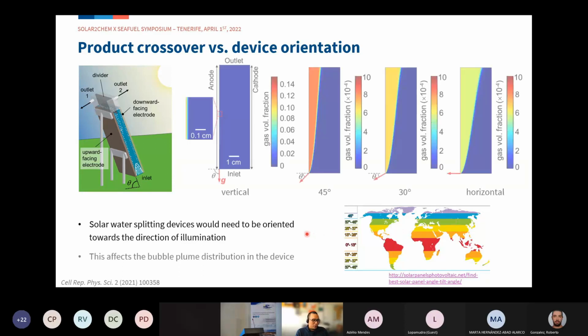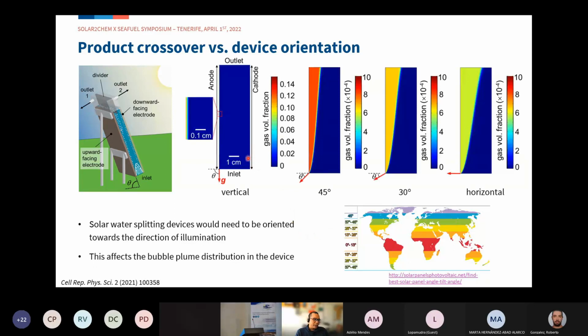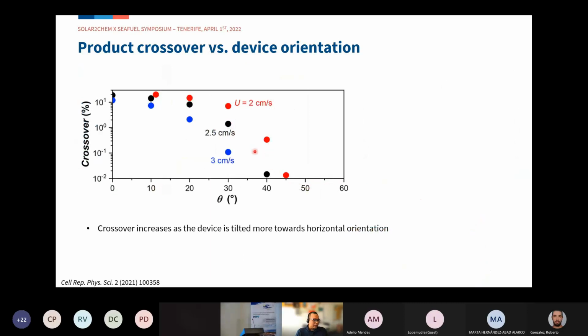Now what happens to the product crossover? We show over here the bubble plume distributions, or the gas volume fraction, as a function of the orientation angle. Under vertical configurations, the bubble stays very close to the electrode, and as we tilt towards horizontal, the bubble plume moves away towards the other side, and crossover can actually be exaggerated. The results are summarized here as crossover as a function of the angle, and the crossover increases as the device is tilted towards a more horizontal orientation.